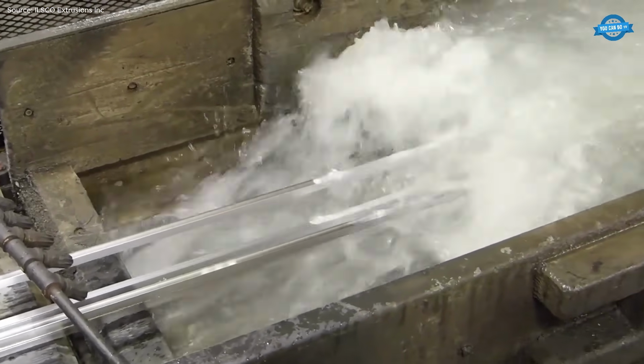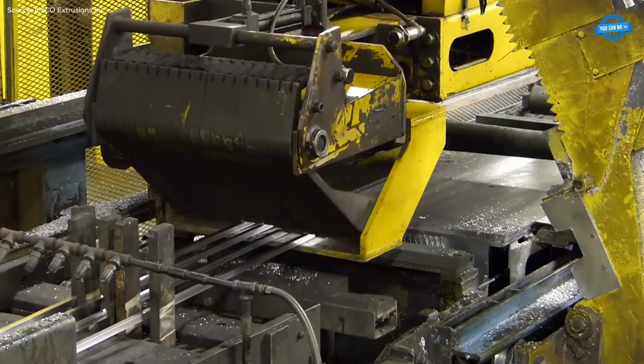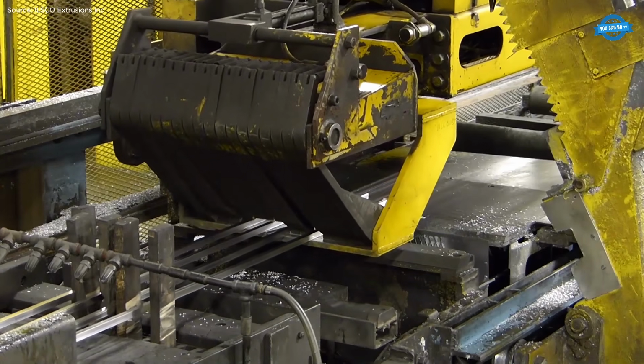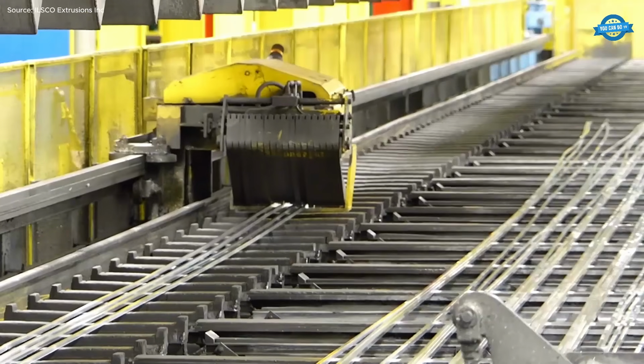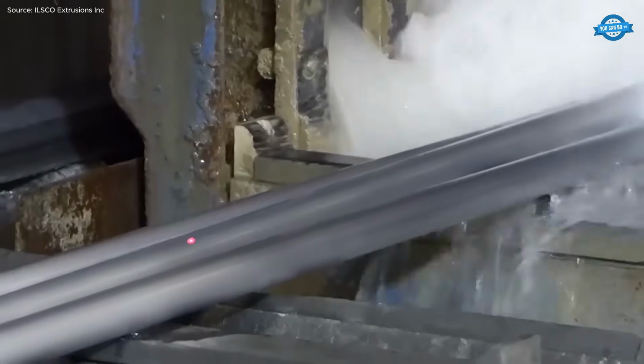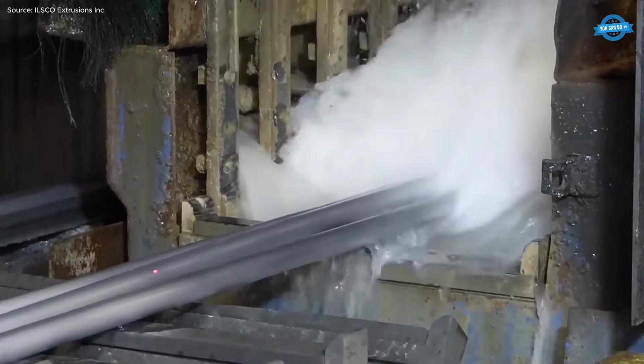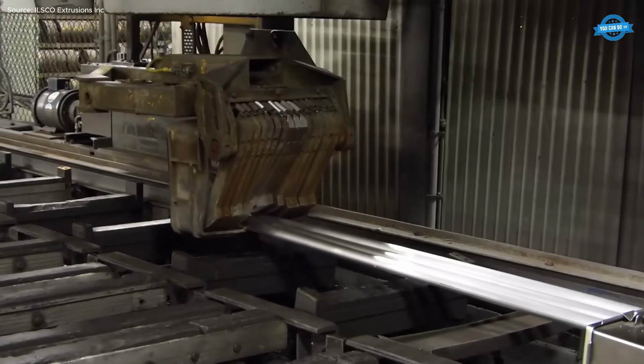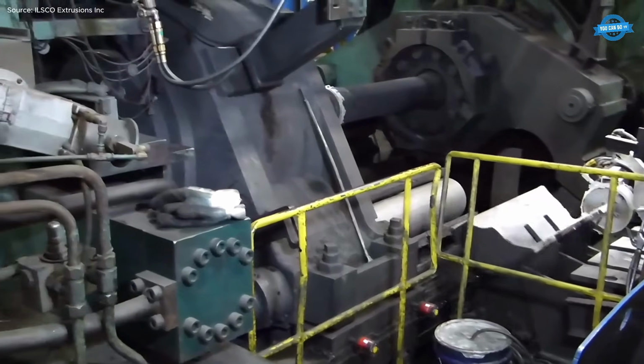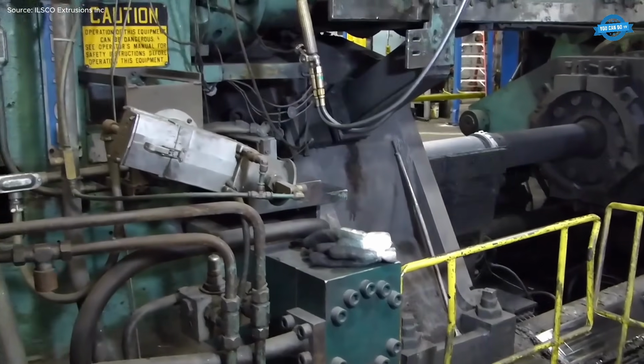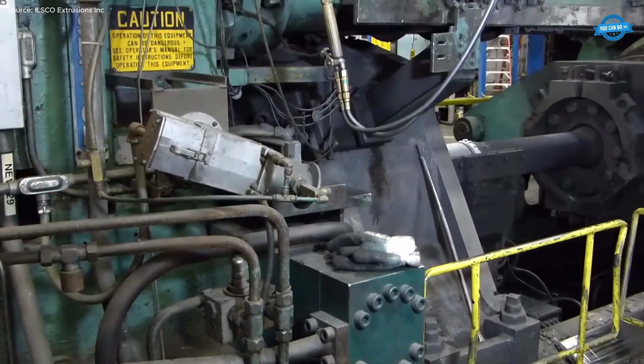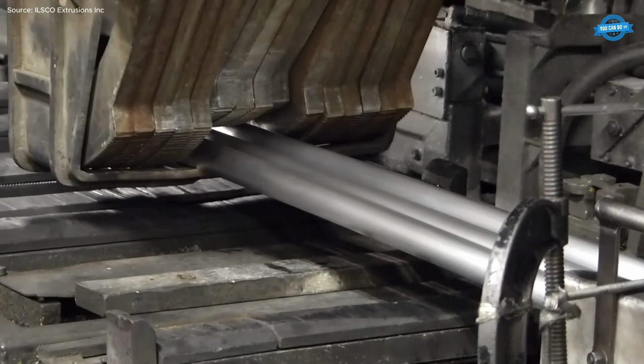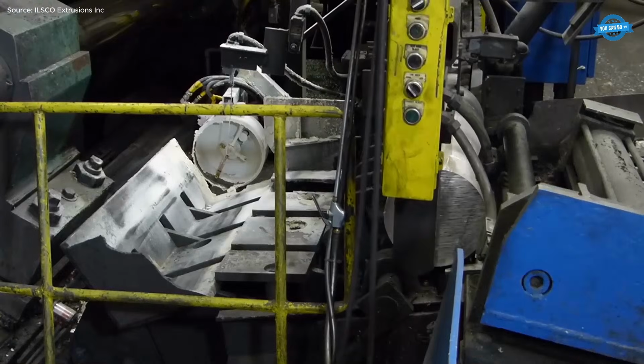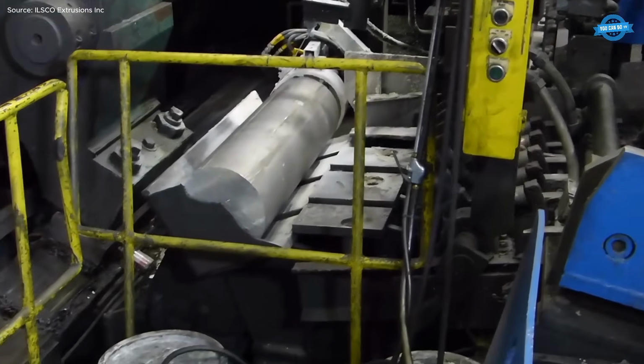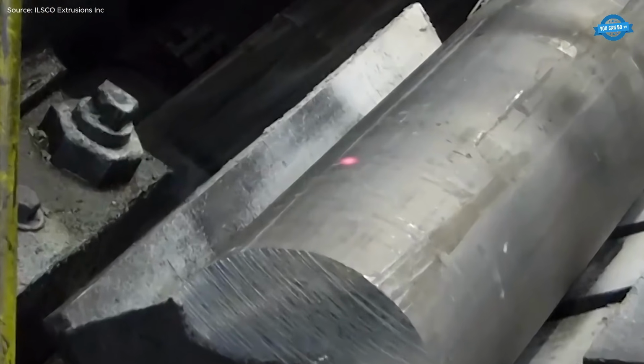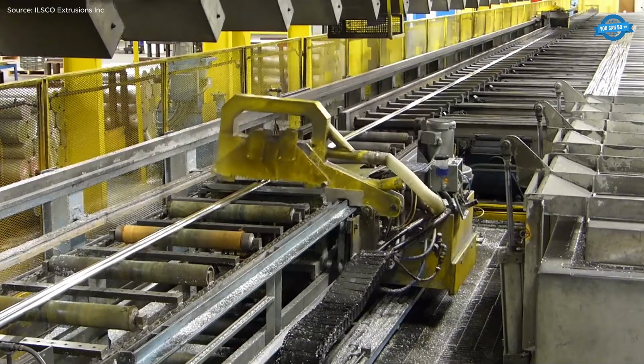As the extruded profile exits the press, it is rapidly cooled using water quenching to ensure the proper microstructure and mechanical properties. A puller system guides the hot extrusion along a runout table, which is synchronized with the press. Maintaining precise temperature control at multiple stages, including the billet, container, die, and press exit, is critical to ensuring high-quality output. Infrared laser cameras monitor and log these temperatures in real time.